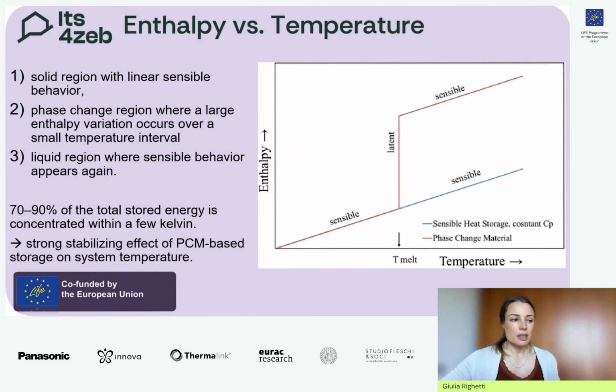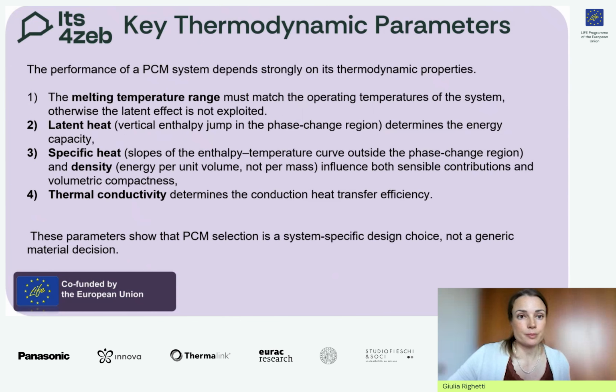But typically, the great majority of the total energy stored is in the second region, so it's concentrated in just a few kelvin around the melting temperature. And this explains why temperature is not useful anymore, but also explains the strong stabilizing effect that these latent storages can have on the system temperature.